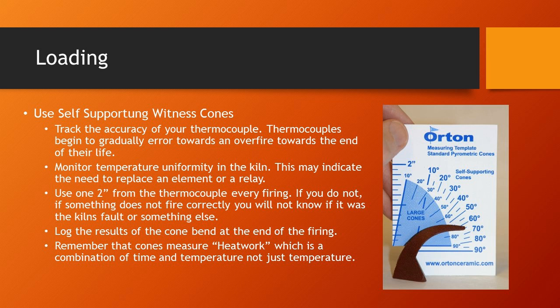We always recommend self-supporting cones. You can get them from your local distributor. If at the very least, put one about 2 inches from the thermocouple. And the thermocouple, as it wears towards the end of its life, will start drifting towards an overfire. Once it starts doing that, you'll see the cone on each additional firing get lower and lower and lower. And that's a good indication that your thermocouple needs to be changed.